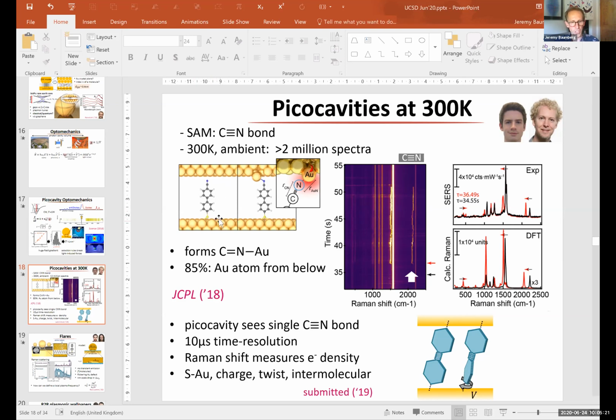Because the field is vertical, of course, we see only a particular part of the Raman, and indeed it seems to be correct that if we get better at understanding this, then we should be able to predict from the Raman spectra, the intensities, exactly what the orientation is. The problem is what people have already alluded to, that you have a huge number of electrons very close to the molecule. So you have to understand how all the dipoles in the molecule react to these image charges, so the phonons can also move from that. This is also a bit like chemical shifts. There's a whole confusing literature in the Raman scattering community about all these effects.